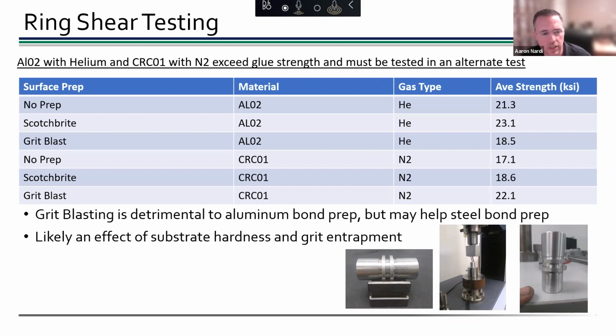However, when you go to the CRC01, which was sprayed onto steel in this case, we see that the grit blast is actually the best. So here we're seeing what we believe is the effect of contamination, with aluminum being able to grab onto that grit a little bit better. We think we're seeing bond line contamination issues with grit blasting on the 6061, whereas we don't see that on the steel.